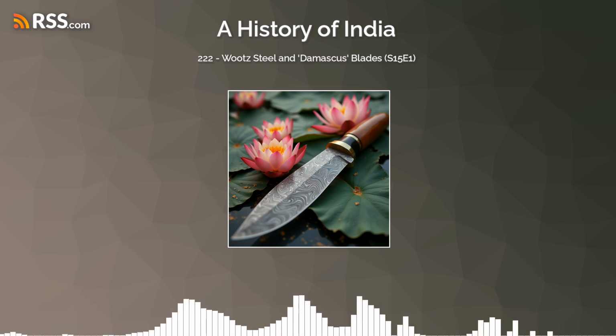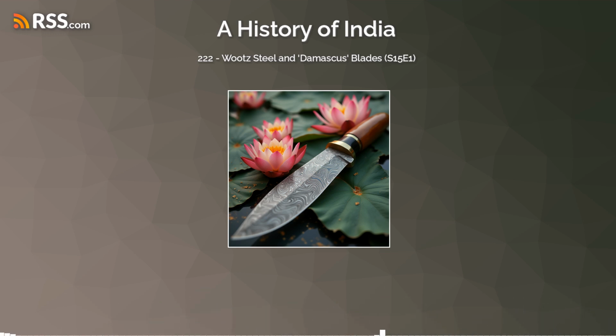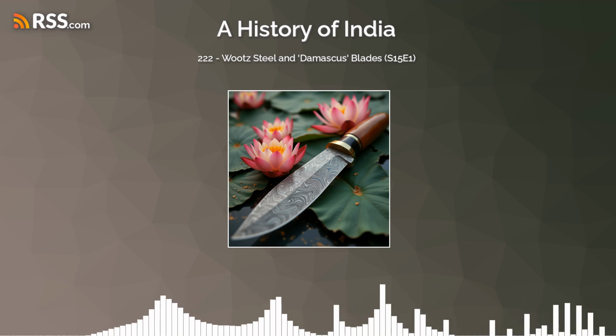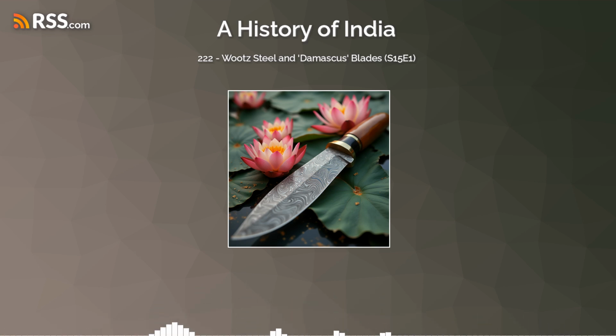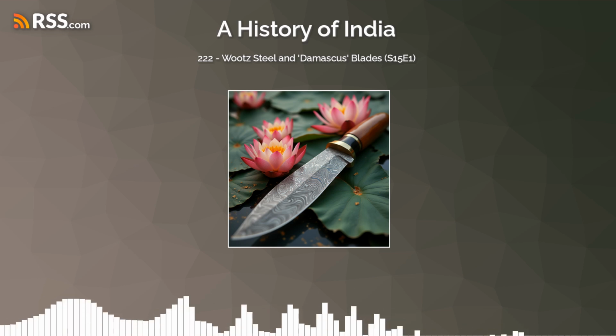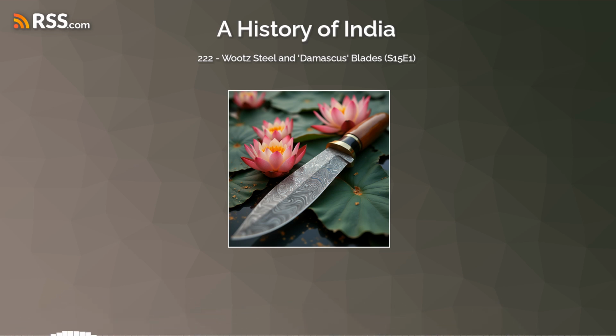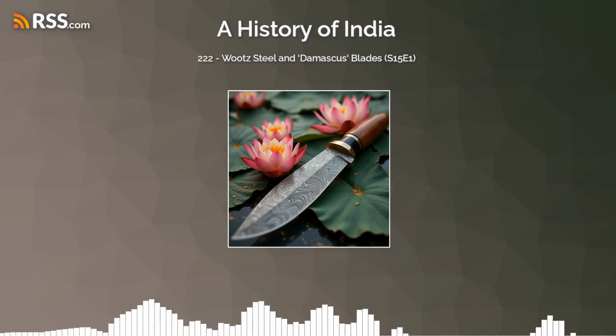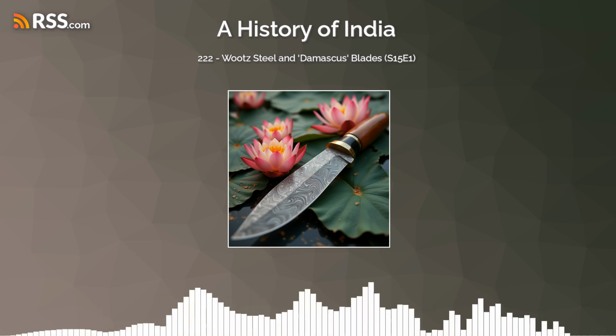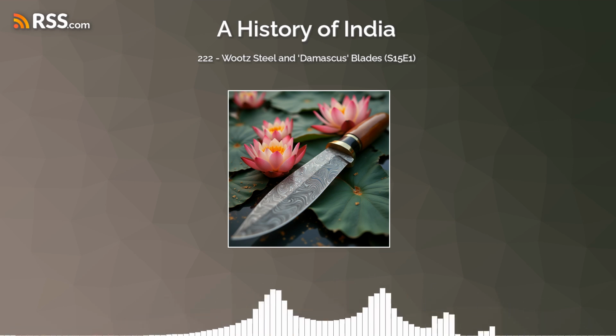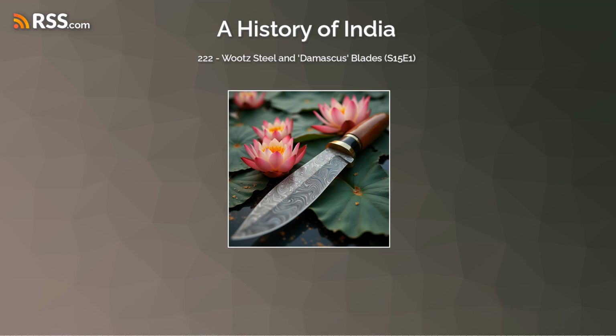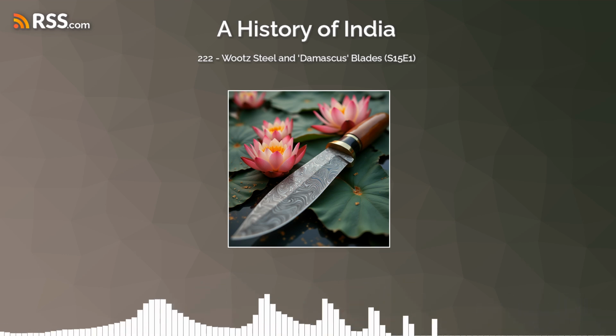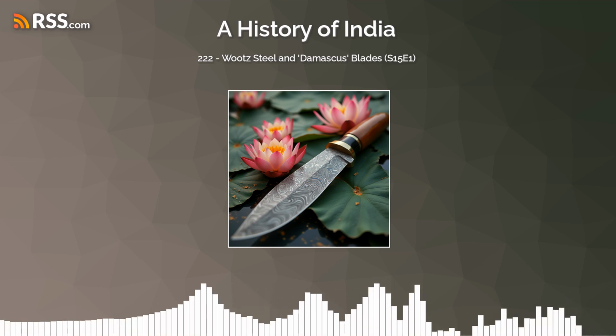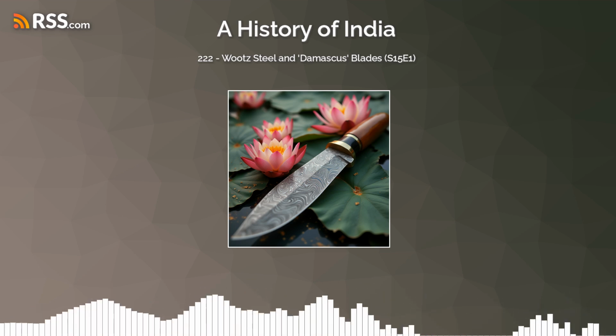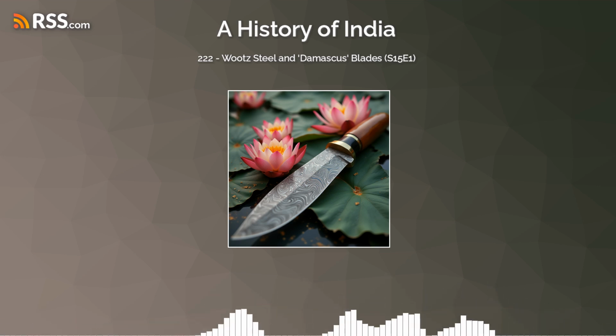All right, the main things were very carefully selected: iron and a carbon source. The iron had to be clean pieces of wrought iron, or what's called bloom iron, but crucially, it had to be low in phosphorus and sulfur. Why was that so important? Because those elements are real troublemakers in steel. They cause something called hot short cracking. Basically, the steel becomes brittle and just crumbles when you try to forge it hot. So getting rid of those impurities right at the start, or using iron that was naturally low in them, was absolutely critical to end up with an ingot you could actually work with. Makes sense. And the carbon source? That was usually hardwood charcoal, crushed up finely.